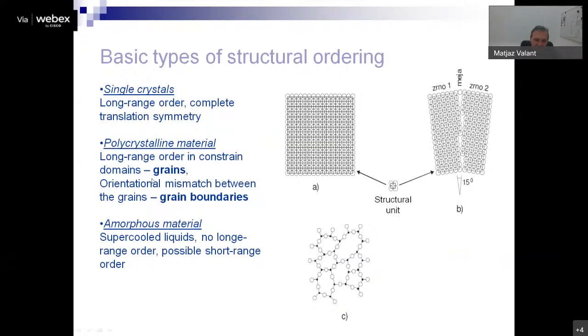In this material, we have domains, which we call grains, that are actually single crystals, and they exhibit long-range order, but they're constrained within the domains, and one grain towards the other grain exhibits some orientational mismatch between the crystals. This is shown here. We have one grain and we have another grain, and there is some mismatch in between, which we call grain boundary. And then we have a material with even less ordering, and we call this amorphous material,